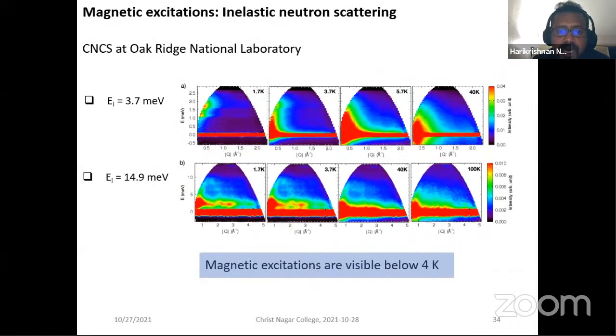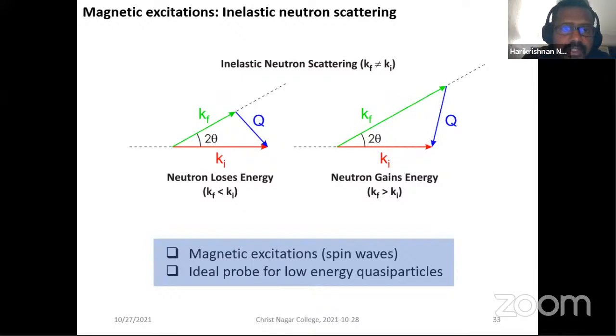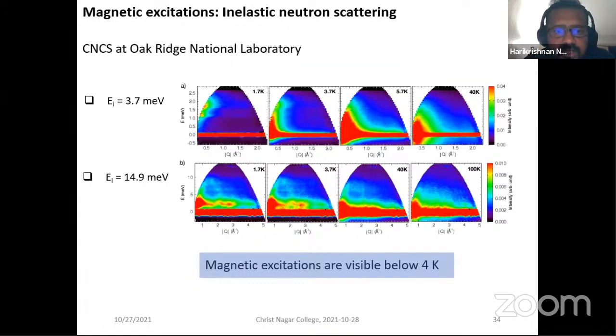Now, what can we say about the excitation? For the excitations, you have to do inelastic neutron scattering, because you have to see how much energy is transferred to the system and then find out what those excitations within the system are. It is through this experiment that you would probe the quasi-particle. If there is a quasi-particle like a Majorana fermion, you should be able to understand that through inelastic neutron scattering. Now, when you do that, you see patterns like this.